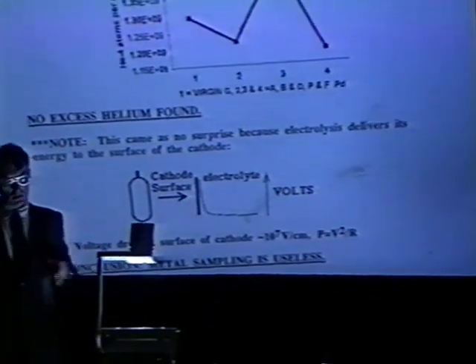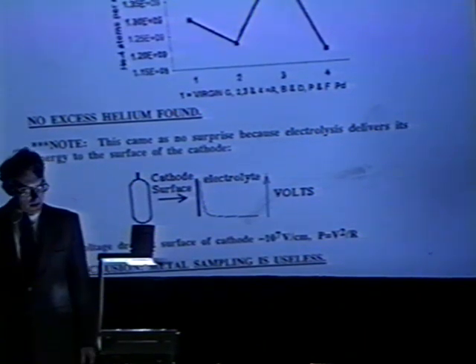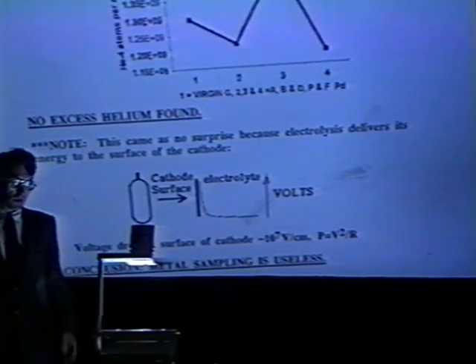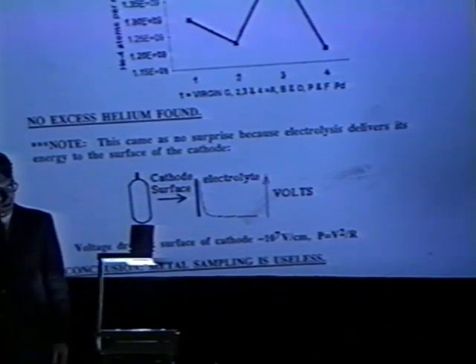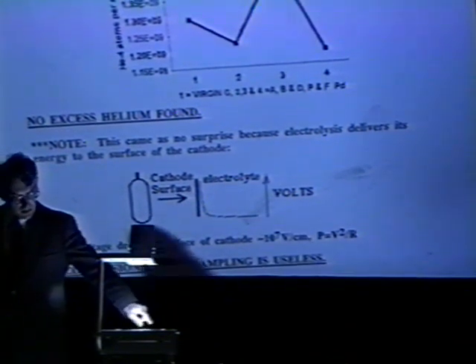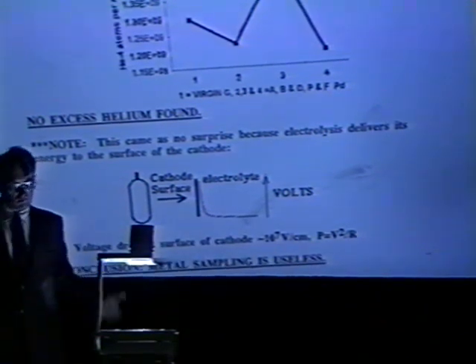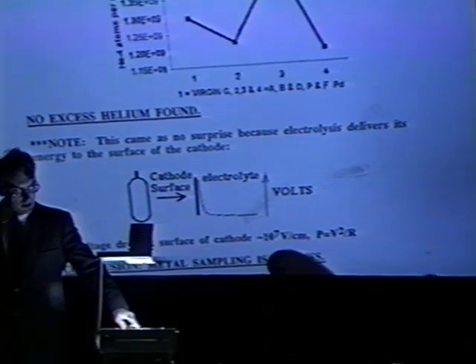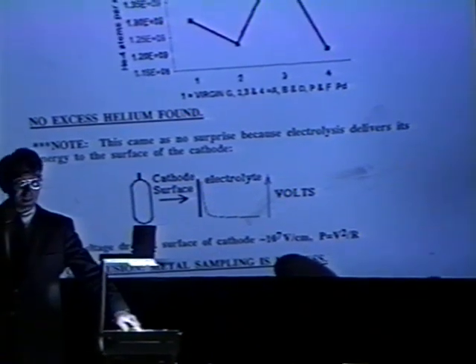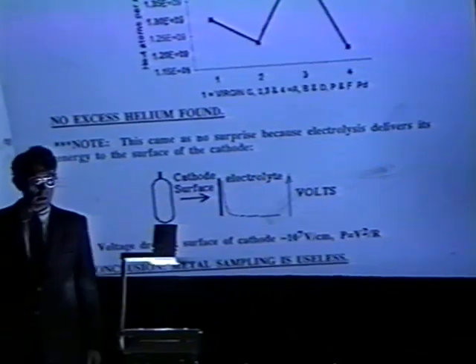So this is not really a surprise because the electrolysis delivers its energy to the surface of the cathode. So I would expect the reaction to occur at the surface. Just thinking about it, I would. You've got something like a 10 to the 7 volt per centimeter drop at the cathode surface. There's a lot of driving force there, if you will. So my conclusion is that I kind of expect cathode analysis of the metal to be sort of useless, but don't take that as too strong a statement because it's not quite that simple.